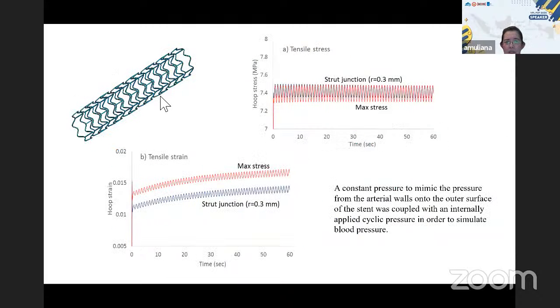So this also just shows you another design of stent when we look at cyclic loading. When you do loading, unloading, because of the degradation and also the viscoelastic effect, you would see the hoop strain here continuously increasing with time. At some point, you cannot keep on with this continuous strain increase, right? At some point, it will undergo failure and breaking of this stent. So when we design, we need to have a design criterion in terms of the load bearing ability and the limit design. Then we could do a proper design to avoid a catastrophic failure.